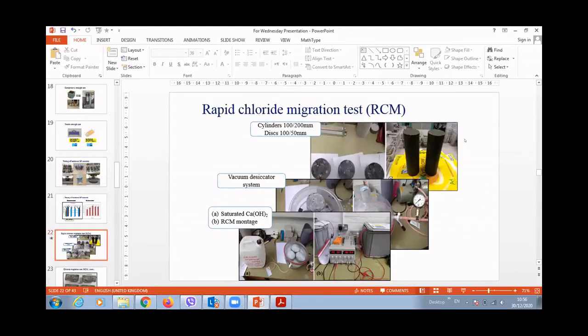The other test we carried out is the rapid chloride migration test for durability. A disc of 5 centimeters depth and 100 millimeters, or 10 centimeters, diameter was saturated in calcium hydroxide, after the vacuum process, to prevent any migration of other cations or anions through the system.